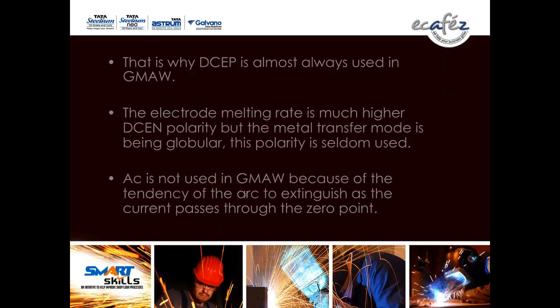That is why DCEP is almost always used in GMAW. The electrode melting rate is much higher in DCEN polarity, but the metal transfer mode is globular. This polarity is seldom used. AC is not used in GMAW because of the tendency of the arc to extinguish as the current passes through the zero point. So polarity is very important. Always use DCEP.